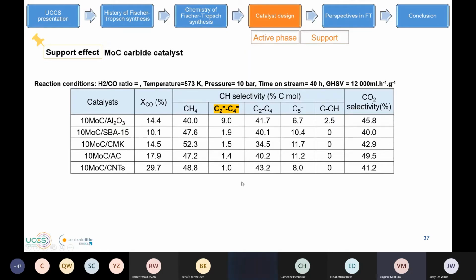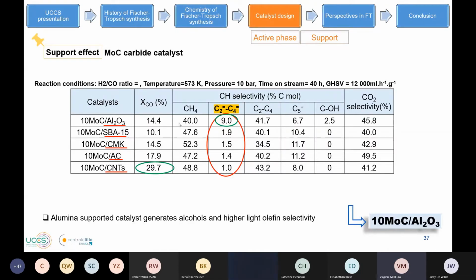So let's talk now about active phase and support. For molybdenum carbide, we used molybdenum carbide on different supports. And what we observe, for example, is a lot of interesting conversion with carbon nanotube support. But if we look at the selectivity to olefins, we observe higher olefin selectivity with molybdenum supported on alumina. So we have better interaction between our active phase and the alumina support, and it also produces a little quantity of methanol. So for molybdenum, it seemed that the best support with better interaction was alumina.